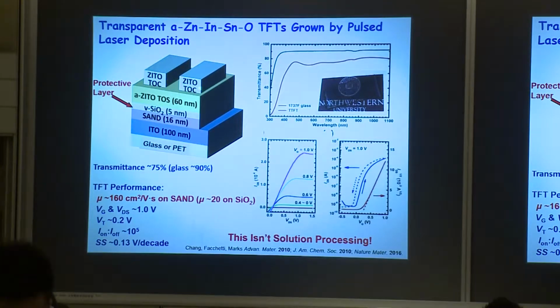And then we're going to change the composition of the ZITO, zinc indium tin oxide. And A here means amorphous, and this is the source and drain. This is a transparent array of transparent transistors on glass. And you can see they're really quite transparent. How good is the performance? The mobility is 160 on SAND. I mean, that just blows amorphous silicon away. On silicon dioxide as the gate dielectric, it's about 20. So the SAND makes a big difference. So very nice pinch-off, very low hysteresis, transparency, really impressive.